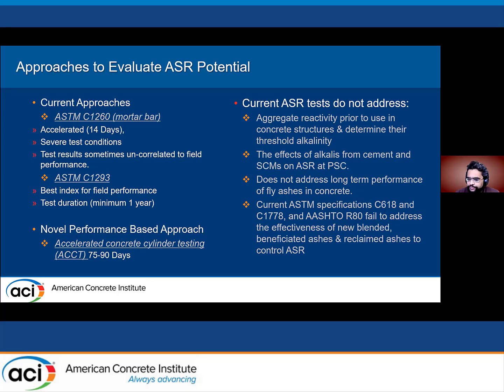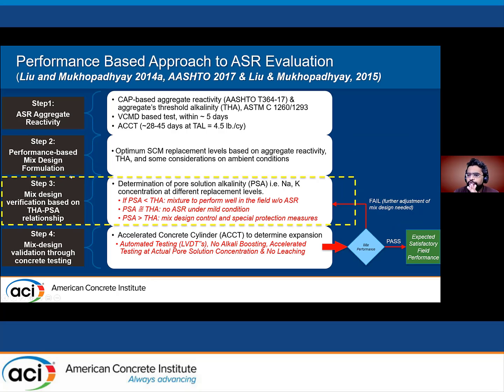So the new approach, which is the accelerated concrete cylinder test approach, presents a more performance-based evaluation of ASR potential, and also designs the optimum replacement percentage for different SCMs. Yes, so there are 4 different steps to this entire evaluation. The first is determining aggregate reactivity, and we could be using any method such as the CAP based, which is cumulative aggregate potential based reactivity, or the VCMD test, which usually takes around 5 days, or the ACCT test, which takes about 28 to 45 days. The essence here is to determine what the aggregate reactivity is in the first step.